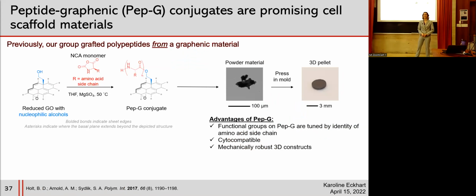So before I came to CMU, the Sydlik group was already working on a pathway to create functional graphenic materials with tunable surface chemistry. And the approach they were using was grafting a peptide from the surface of the graphenic material. So they started out with a reduced graphene oxide that has these nucleophilic alcohols. And then they treated it with an N-carboxy anhydride monomer to polymerize a peptide from the surface. And this resulted in a powder material that was cytocompatible and where the identity of the functional groups on the surface could be tuned by the identity of the amino acid side chain of the NCA. And these powder materials could be pressed into a 3D pellet that was mechanically strong.